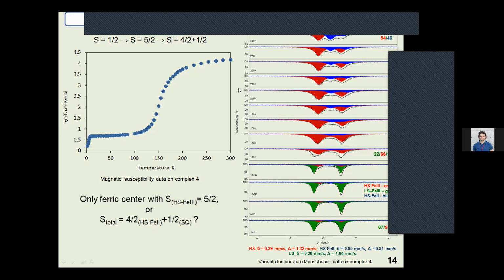And an unexpected result was obtained after detailed analysis of Mössbauer data. At high temperature the spectrum is characterized by the presence of two doublets. The first one corresponds to the high spin ferric configuration, while the second one, surprisingly, was attributed to the high spin ferrous ion. The relative areas of these two signals are estimated as an almost equimolar mixture at 300 Kelvin.